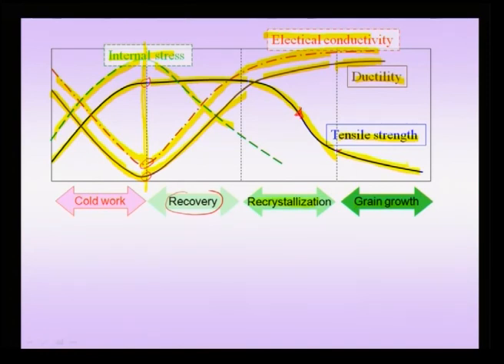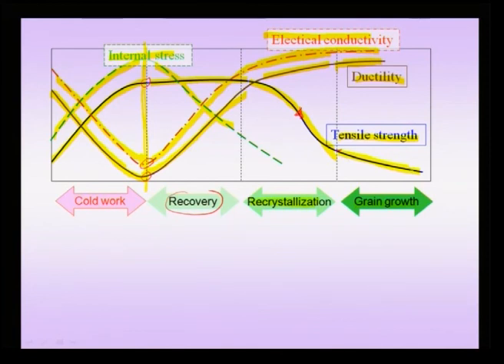So we see here in this slide, which I summarize now, that when I take my cold work material with a high defect density and hold it at temperature, the processes involved, the technical terms being used, are recovery, recrystallization and grain growth. At each one of these stages, some of the properties tend to come back to their original state. During cold work, for instance, the electrical conductivity comes down and the ductility comes down while the strength increases, and most of the strength continues to remain even though I have caused a recovery process. The maximum fall in strength actually takes place during the recrystallization process, and further the strength continues to drop when I cause grain growth. The electrical conductivity actually recovers to most of its peak value during the recovery itself.